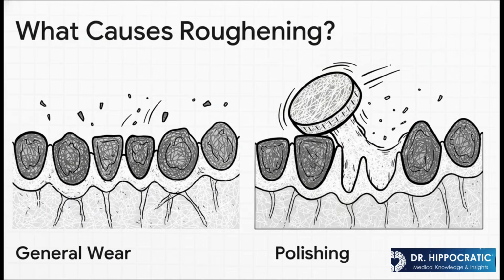So what's actually causing this roughening? It really boils down to 2 things. First, you've got general wear. That's the softer matrix, our mortar, just eroding away and exposing the hard glass particles, our cobblestones. But here's the really ironic part. Even the act of polishing the filling can make it rougher by stripping away that soft matrix and leaving those hard glass cores poking out.